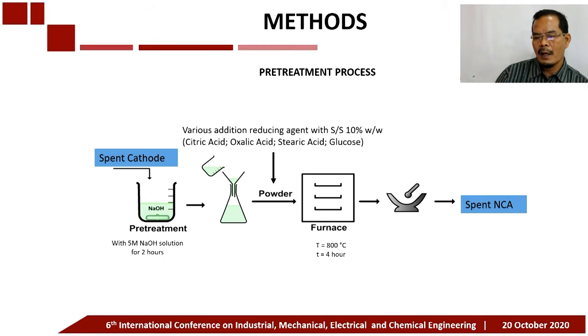The first step is pretreatment. Here, the aluminum sheet dissolves in the NaOH solution. On the other hand, the cathode material is not dissolved in the solution. The solid-liquid mixture was then separated by filtering. The reducing agents used were citric acid, oxalic acid, stearic acid, and glucose. The solid mixture was then heated in a furnace at a temperature of 800 Celsius for 4 hours. The solid was then cleaned, and the product was the spent NCA.